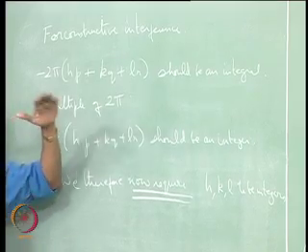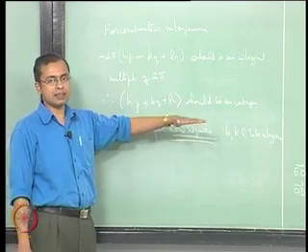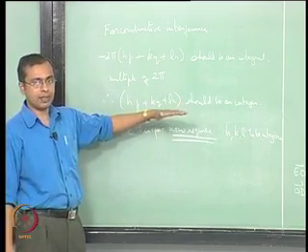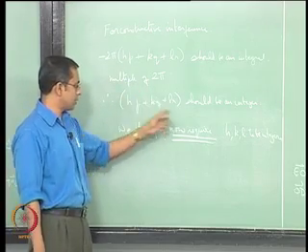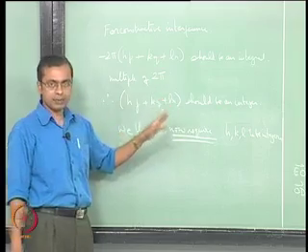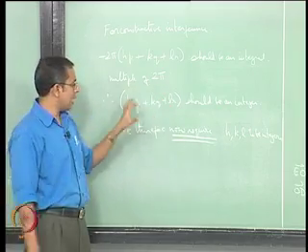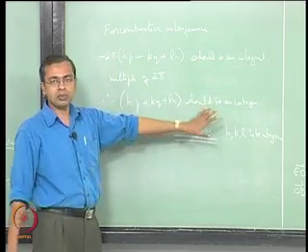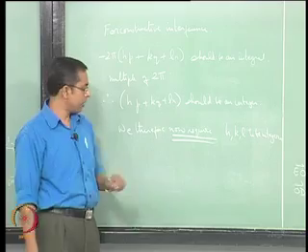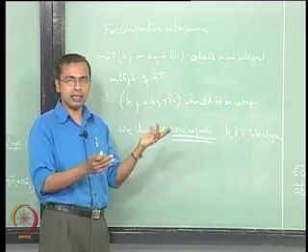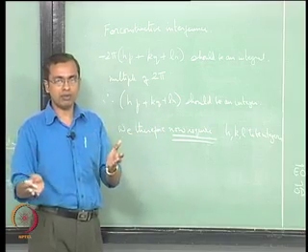In our derivation, originally h, k, l could have been anything, but the conditions that interference places on these relationships create a situation where h, k and l arrive at this particular sum, where they are multiplied by p, q and r respectively, where p, q and r are integers, and that sum should be an integer. For this to be true regardless of the values of p, q and r, we can guarantee this only if h, k and l are also integers. So h, k and l, which could have been anything earlier on, now have to be integers for constructive interference to occur.